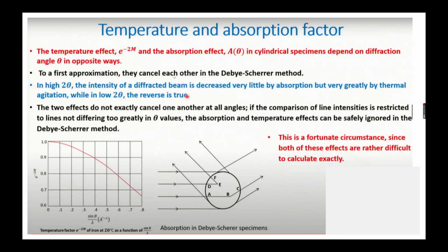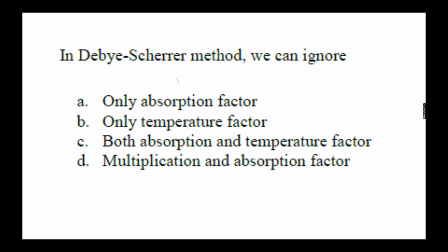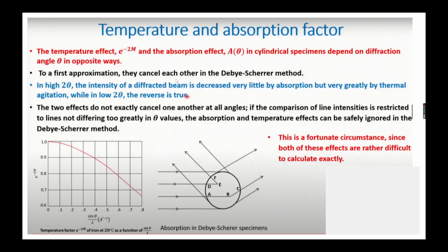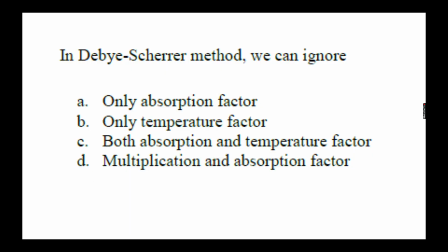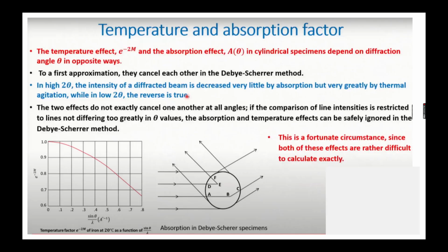So here we can cancel both the temperature and the absorption effect; in this method we can ignore them. It says the two line effects do not exactly cancel one another at all angles. If the comparison of line intensity is restricted to lines not differing too greatly in theta value, the absorption and temperature effect can be safely ignored in the Debye-Scherrer method. So in the first approximation, we can ignore both the temperature and the absorption factor. So the answer is C.